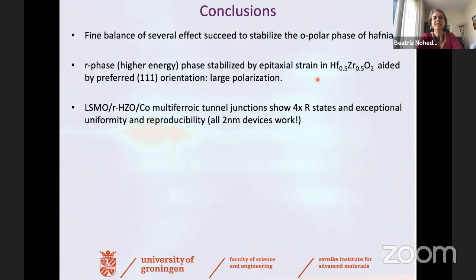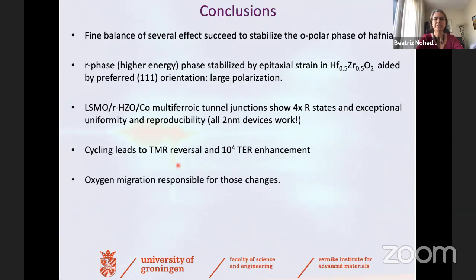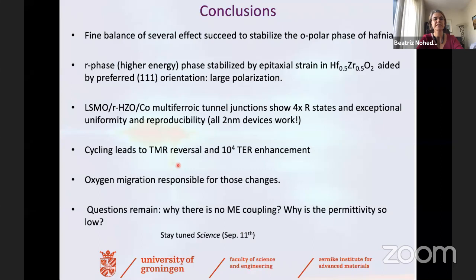The multiferroic tunnel junctions made with this rhombohedral phase show four resistance states and exceptional uniformity and reproducibility. All the 2-nanometer devices work. And the cycling leads to reversal of the TMR effect and a 10^4 enhancement of the tunneling electroresistance effect of the material. We see that oxygen migration within the tunnel junction is responsible for those changes.